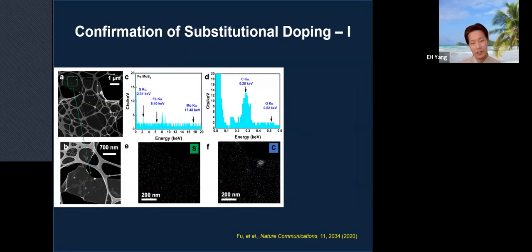So again, this work was published in Nature Communications, and usually Nature reviewers are very picky. The reviewers still want to see double, triple confirmation that there is no other effect, right? Everything has to be 100% sure that everything is from these atoms, not from other molecules, not other adherents. So what we did was to perform additional experiments. Basically, my student had to come back from vacation. Actually, the first review came in on December 26th, right? So that's 2019. And then basically it's one or two months of craziness, getting these additional results. So basically that's what we did here.